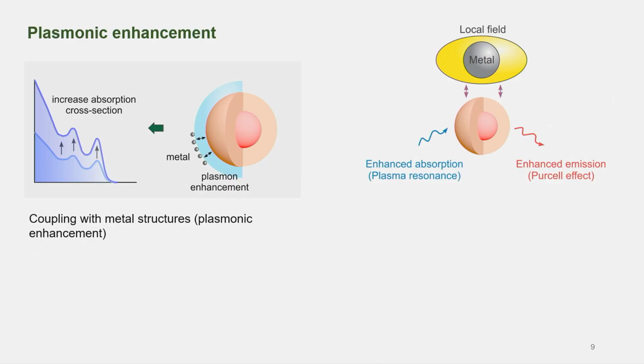The second strategy we think about is plasmonic enhancement. We want to have some metal structures close to the quantum dot surface, and it could work through two different mechanisms. One is that these metal structures absorb the energy of photons and translate it into oscillating dipoles, and these dipoles can transfer the energy to the quantum dots. So this is another way of seeing it as a light absorber. The other way is enhanced emission, which we call the Purcell effect. We can have an enhanced radiative rate.